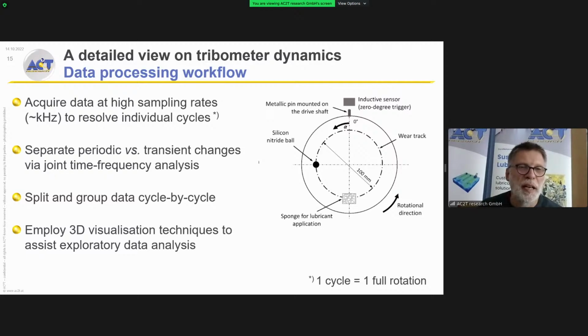So here again, the schematic view. So we have a pin on the disk. We have some sponge which applies a certain defined amount of lubricant film on the disk, and we have a sensor which indicates the zero position so that we can detect the number of rotations of this disk. The core thing here is that you have to acquire the data at enough high sampling rates to resolve, let's say, the individual cycles. So that means if you have, for example, a 50 Hertz or 3000 RPM rotations, then you need at least, let's say, 5 kilohertz sampling rate to resolve in a reasonable way the individual rotations.